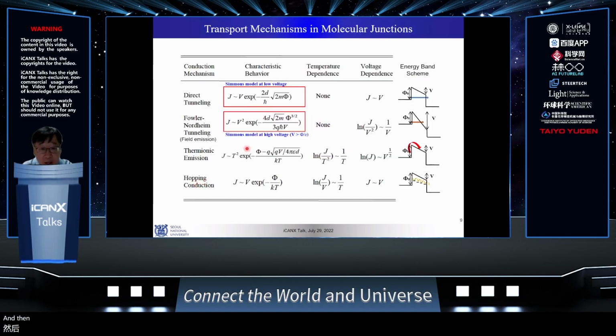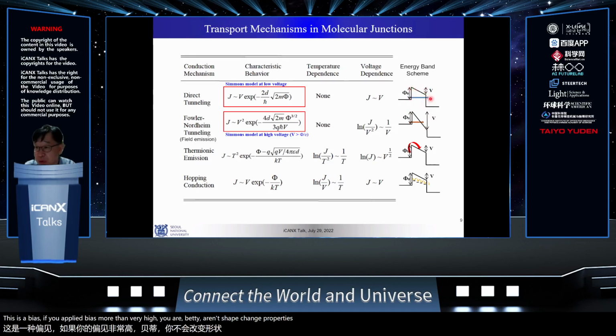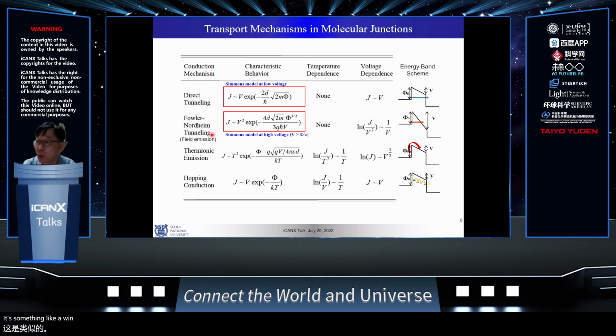And then when you apply a bias more than the barrier height, your barrier shape changes from rectangular type to triangular type, which is actually the onset of field emission. We call it Fowler-Nordheim tunneling or field emission, which is the same. It's something like in an old cathode ray TV, they apply like 600 volts, and it creates field emission of electrons shooting from the filament. So this is the actual onset.